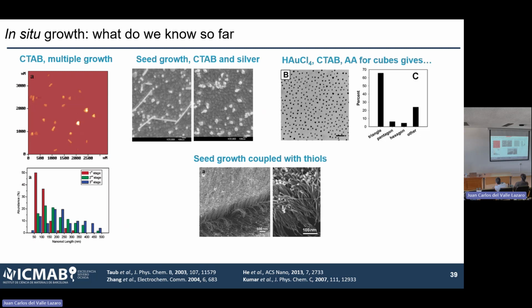I put these examples here for a reason. The first one is that we do observe the possibility. There have been some studies showing that by changing the growth, we can control, very poorly, but we can control which kind of particle we observe. So to a certain extent, it has been shown that the same kind of control that we have in colloidal solution is at least theoretically possible in in situ growth systems. In this study, which is very interesting, they used conditions that in solution would give you cubes, and instead they obtained triangles, which tells us that what we learned in colloidal solution is not necessarily 100% translatable to in situ growth.